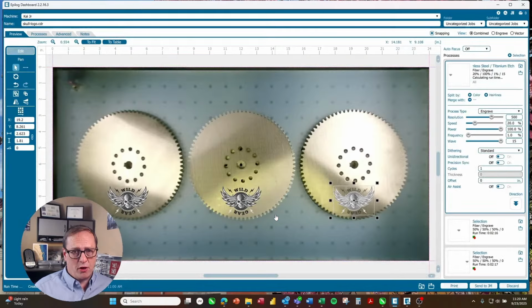So with the etch mark, we're actually trying to get some depth into the metal. When you're going for that kind of mark, first of all we set our resolution. This is basically the dots per inch, which is also our line spacing. So on a deep engraving, I wanted about 500 DPI. Speed, we're going to slow down so we get that depth in there, and we're going to turn that down to 20%. I'm going to take my power all the way up to 100%.